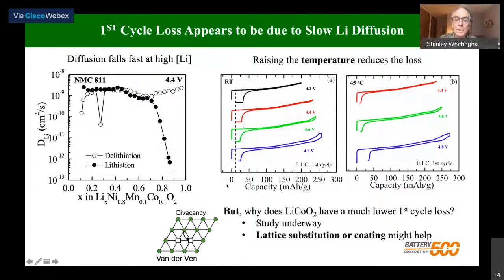Okay. But on the right-hand side, I'll show you another important parameter. If diffusion is rate limiting, then if we raise the temperature, this should help solve the problem. So I show you here 4 curves charged to different voltages, 4.2, 4.4, 4.6, and 4.8. And you can see we get better capacity the higher we charge, so the more lithium we take out. But you'll also see that we're now getting separation of the charge and discharge curves. This is because of surface reactions damaging the surface of the material.